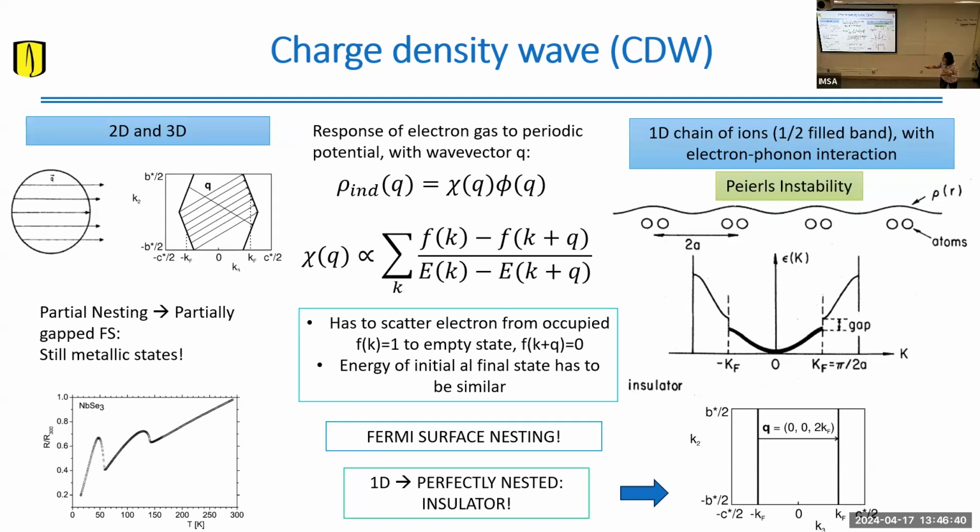So this is an example in niobium triselenide, in which you have 2 different transitions to a charge density wave due to 2 different wave vectors that nest different portions of the Fermi surface. Right at this transition, the resistance of the material increases because it opens a gap right at those transitions. But nevertheless, eventually the metallic state will win the fight, and then you have another transition to a charge density wave.